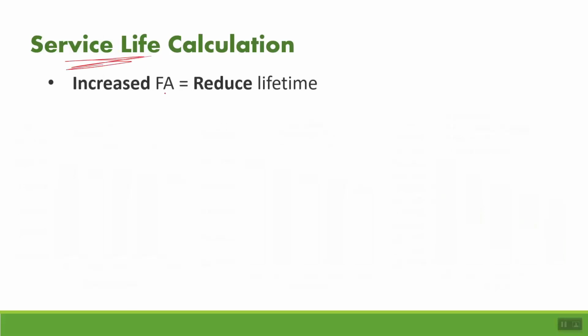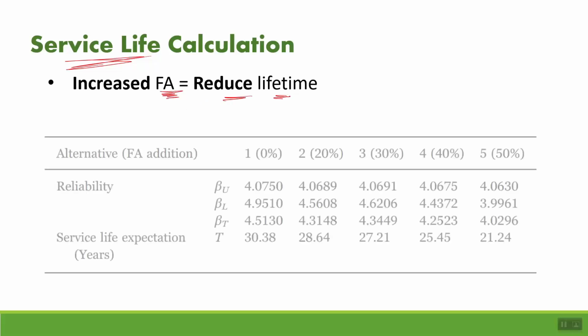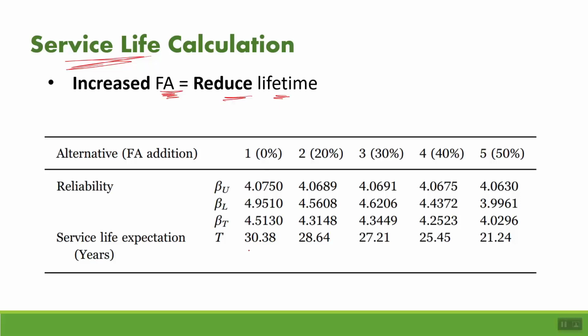But by performing service life calculation, by increasing the fly ash replacement ratio, we reduce the lifetime or service time of the structure. As can be seen from this table, by increasing the percentage ratio from 0%, 20%, 30%, and more, the service life of the structure is reduced from 30 years, 28 years, 27 years, 25 years, 21 years for a replacement ratio of 50%.